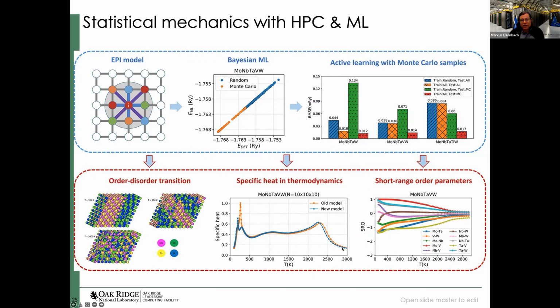And that's also then supported in, if you look at the specific heat, and especially you can identify at the lower temperature the different ordering temperatures now of these binary phases. As you see here in this graphic on the left, the molybdenum tantalum phase is already basically completely ordered, whereas the niobium tungsten phase has still a significant amount of disorder. And also we can measure, obviously, the short-range order in these systems.